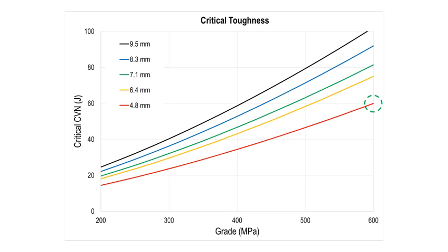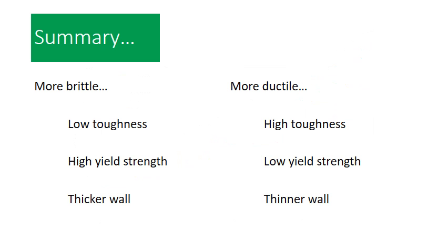And if you think about that, it actually makes sense. Because you've got a much higher yield strength material, you have to have an appropriately higher toughness in order to cancel that term out of the mathematics. So here we would say to ourselves, hypothetically speaking, if we had, say, 40 joules of toughness, that would not be enough to ignore the fracture term. We would have to keep that fracture term in our mathematics as we do our various assessments. Hopefully that makes a little bit of sense.